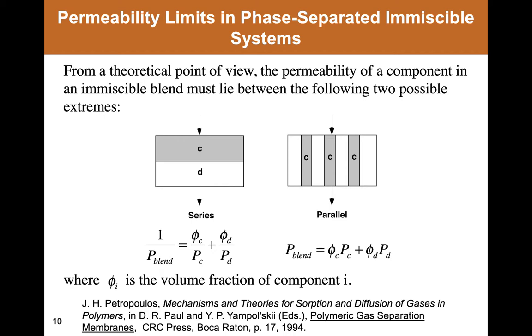One limit for combining two materials in a blend would be simply to have a layer of one material labeled C on the left-hand side, and then underneath it a layer of the second material labeled D, and the transport being perpendicular to this. This would correspond to mass transfer resistance in series, and you can start from Fick's law and derive the expression that's shown below that. That is that 1 over the permeability of the blend is the volume fraction of material C divided by its permeability, and a similar term for D. So this is one limit for what the transport properties can be in a blend of two materials.